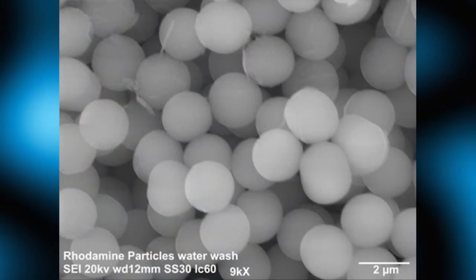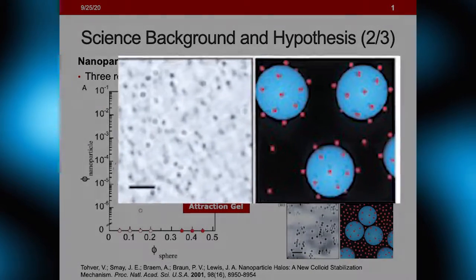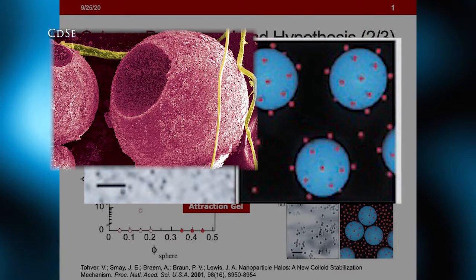And so if I could create a nanoparticle haloing system where I have a large particle that's made of the charge carrying type materials like titanium dioxide, and I have a small nanoparticle that we can use as the quantum dot that is made of these charge generating materials, things like cadmium selenide, lead sulfide, and materials like that, and I could create one nice colloidal crystal structure with those two particles inside of it, I've effectively had a quantum dot sensitized solar cell assemble itself.